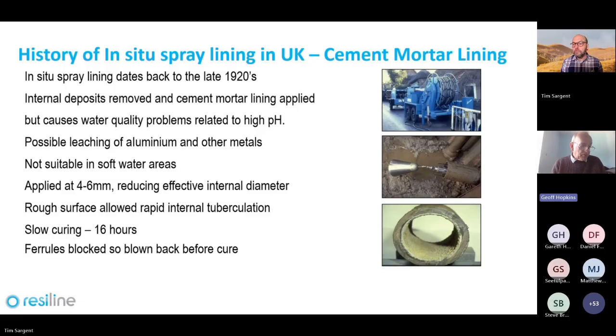Obviously, back in the 1920s and 30s, cement mortar sealed the surface and cement mortar lining was used quite extensively up into the 1980s. The cement mortar sealed the surface and provided an alkaline environment for the old iron pipes, passivating against ongoing corrosion. But of course, cement mortar lining applied inside existing pipes gave substantial short-term water quality issues. So the search was on then. So next slide, please, Tim.